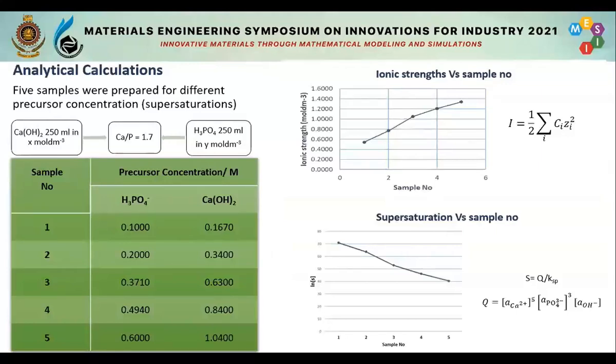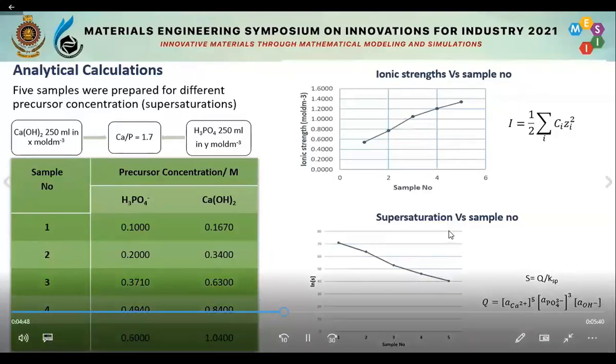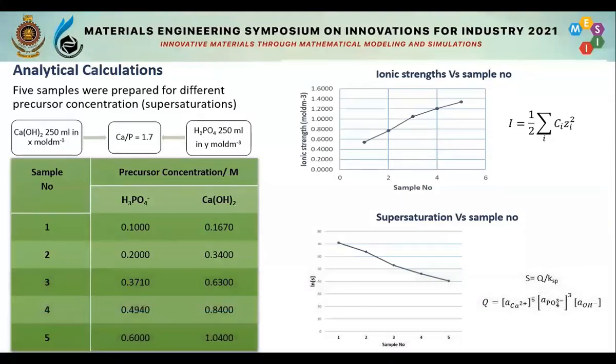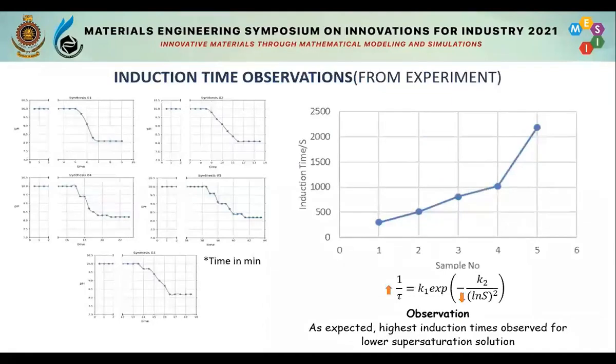In the analytical calculation, we used 5 samples with different precursor concentrations, with the calcium to phosphorus molar ratio maintained at 1.7 for all samples. As you see, the highest ionic strength is observed for sample number 5 with the lowest supersaturation. Accordingly, sample number 1 has the highest supersaturation based on the analytical calculations. As you see, the experiment results in some pH curves.